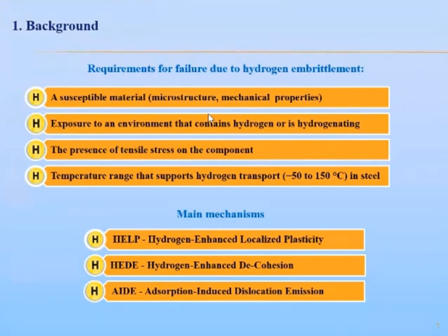And it's worth noting that while cracking mechanisms are similar, the rate controlling processes are very different. And a combination of the main mechanisms that occur under hydrogen embrittlement, these are hydrogen enhanced decohesion and adsorption induced dislocation emission.